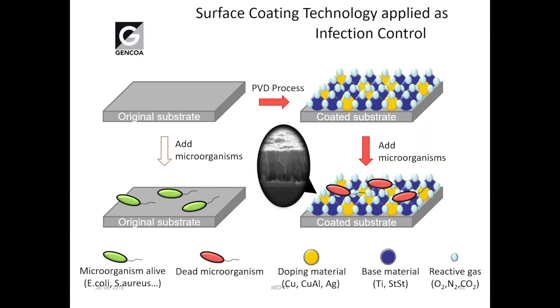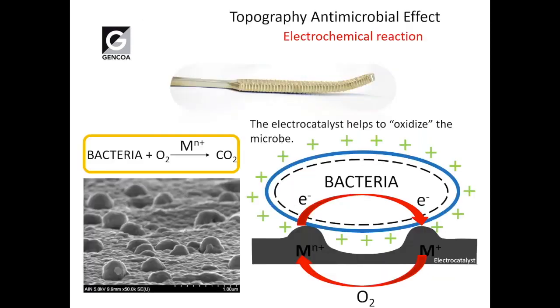To turn it into plain old English, it means that we have very excited electrons at the surfaces, which can drive oxidative reactions, which bugs don't like. And it's reproducible and it's scalable. If we zoom in a little bit more, this is, in terms of the topology, more of what we see is happening at the micro nanoscale. On the left-hand side, the electron micrograph, you can see the kind of scale of the surface we're looking at.